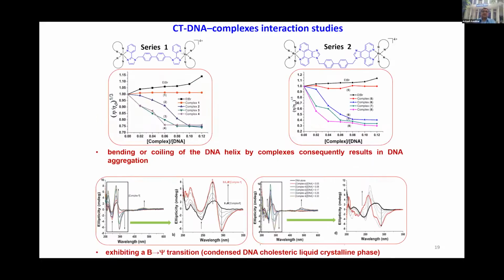And we can also increase the bridging structures, with 2 metal ions anchoring 4 ancillary ligands. And so we can increase the length of this flexible linker as we have. This can give rise to structures which will be able to, as we saw, help in condensing DNA. We have studied this by various techniques such as viscosity on addition of DNA. It evidences condensation of the DNA.